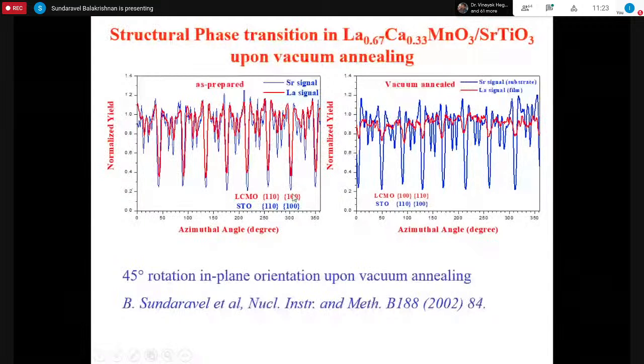So 110 is coinciding with 110 of this substrate. And upon vacuum annealing, there is loss of oxygen and there is some change of structure, and the in-plane rotation turns by 45 degrees. For example, when the dip is 110 for LCMO, for STO, it is 100. So from this, we can tell whether in-plane rotation is there or not.